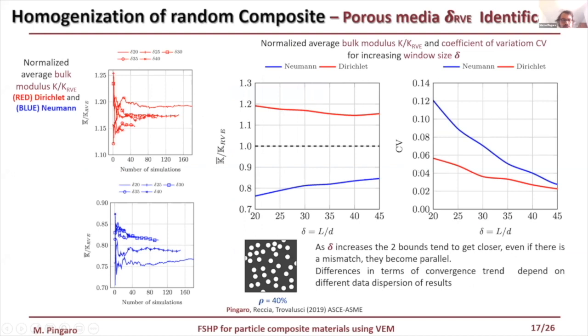Then here is reported the value of the normalized bulk modulus. As the window dimension increases, the two bounds tend to get closer, even if there is a mismatch between the two bounds, because the two bounds became more or less parallel. These differences in terms of convergence trend depend on the different data dispersion of the results.